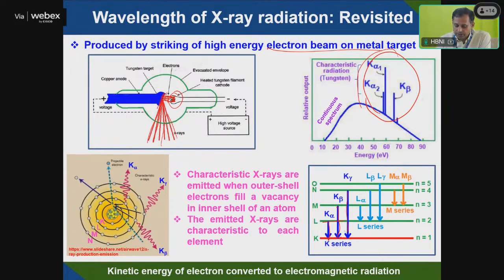So these are characteristic peaks with respect to the element. Like copper has K alpha of 1.54 angstrom. For molybdenum it's 0.71 angstrom. So for a defined element, that K alpha characteristic wavelength is different.